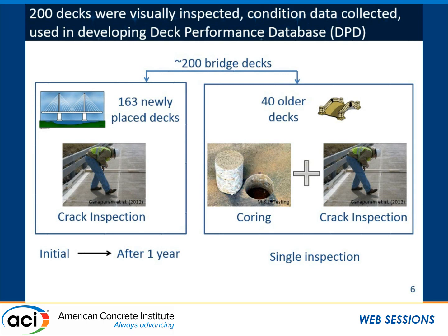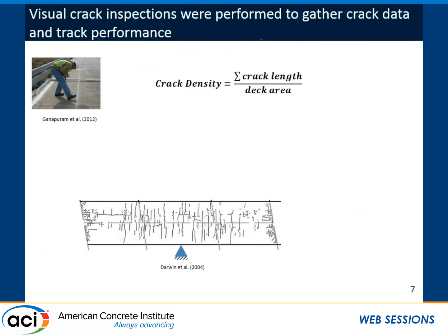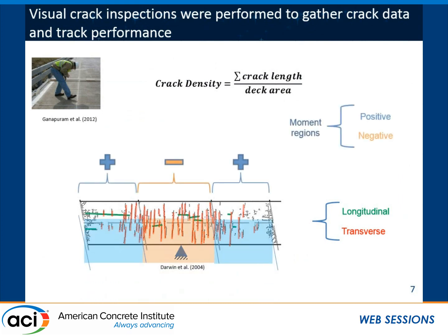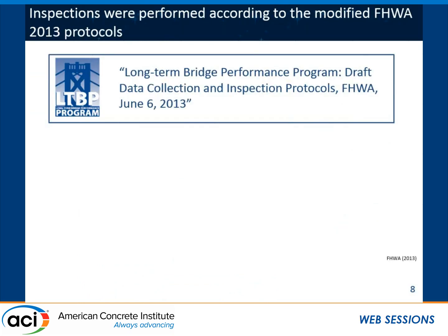For the older decks, we did crack inspections. We also did the coring and measured the chlorides. The crack inspection was used to get something called crack density, which is the length of the crack per unit area of the deck. The unit would be, for example, yard per square yard of concrete. We looked at both longitudinal and transverse cracks. We looked at positive and negative moment areas of the deck.